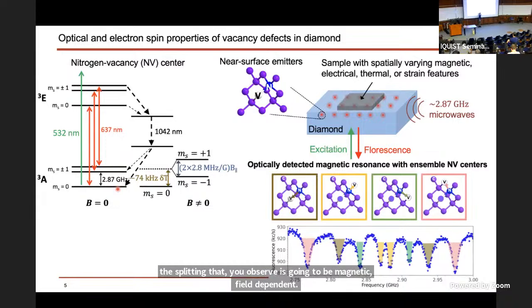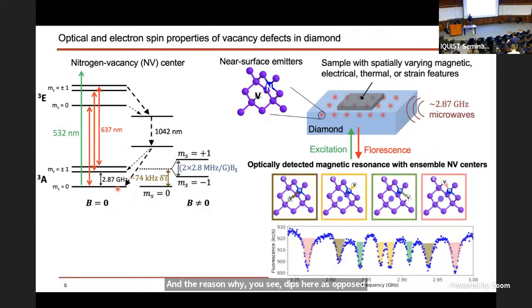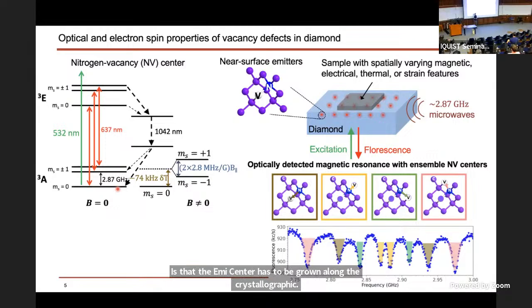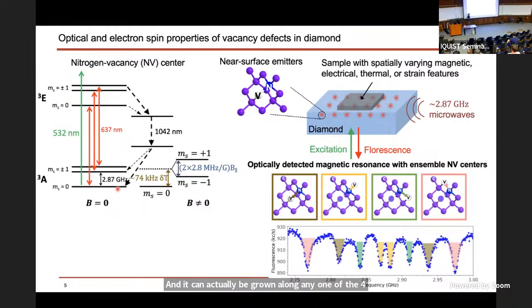The reason why you see 8 dips here, as opposed to 2, which is what you would expect for a single NV center, is that the NV center has to be grown along a crystallographic direction of the diamond. And it can actually be grown along any one of the 4 possible directions in this tetrahedral structure, and so you get 4 orientations. If you have a magnetic field that has a non-zero projection along any of these directions, you see different splittings, and they can be made to be different. And so basically you get a vector magnetometer for free, with the coordinate system of your magnetic sensor being referenced to the diamond crystal.